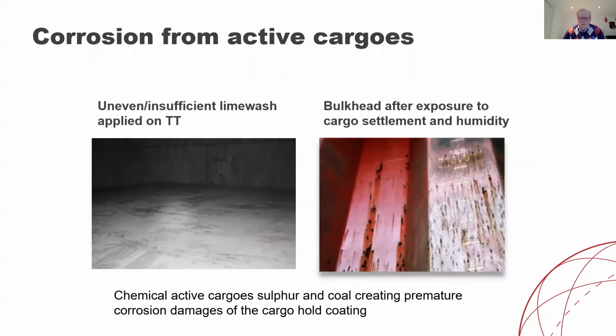On the left-hand side here, they've been using lime wash applied to the tank, you can see here, but also you see the hopper plating in the background. So the whole cargo hold applied with that. But what you do see is that the lime wash is not opaque all over. So that means it's not been applied in the correct thickness, and therefore you will have corrosion when you are loading the sulfur.